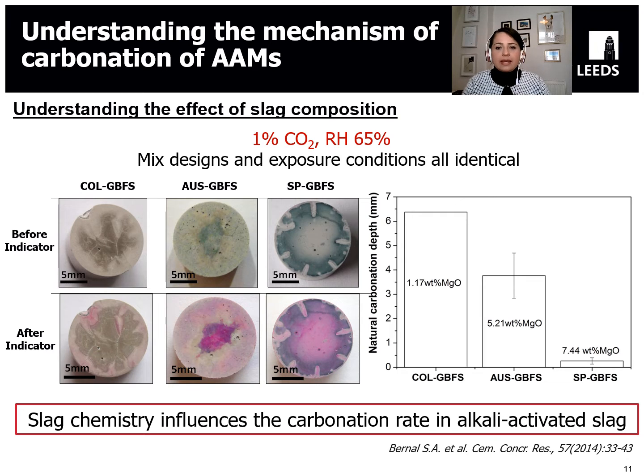But at the time, this study let us identify how the magnesium oxide content of slag has a tremendous impact, one, in the chemical composition of the binder phases that are forming in this type of materials, and second, in the secondary phases that can form, particularly the formation of layered double hydroxides or hydrotalcite, which can act as CO2 sinks within the material. So we identified in this study how, as we increase the content of magnesium oxide in the slag, we can certainly reduce the carbonation of the material. So this also demonstrates that not all alkali-activated slag cements will carbonate in the same way.